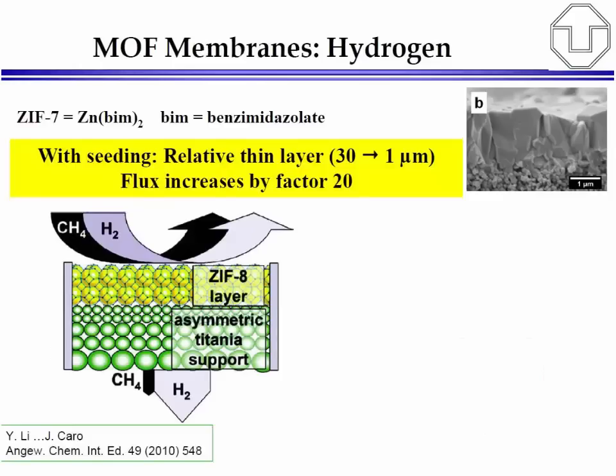On the next slide, one can see that shaping of metal organic frameworks has also had a lot of progress nowadays, especially for separation applications. Of course, you can do separation applications in a breakthrough experiment, in an adsorber bed, but the other way to do it is essentially using membrane technology. And here I refer to the work of Jürgen Caro, who has developed quite selective membranes, for example, for hydrogen separation, using ZIF materials, ZIF-7 in this case. And nowadays it is possible to form membranes on certain support materials, and crack-free membranes are available.